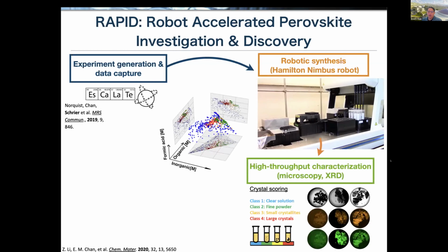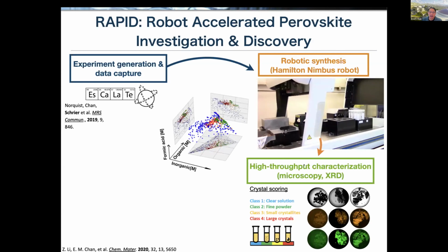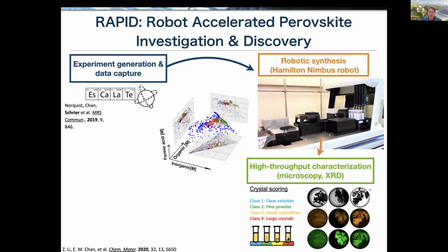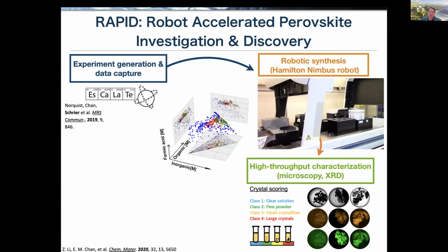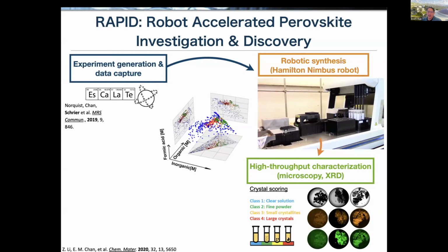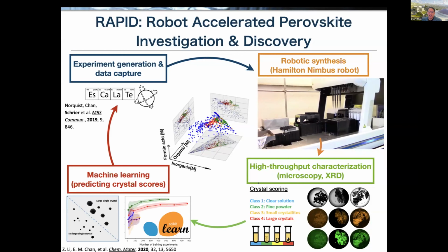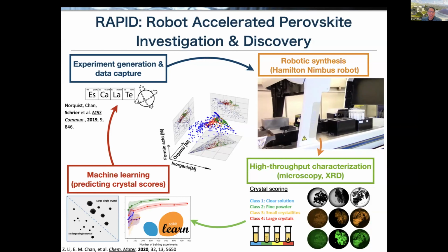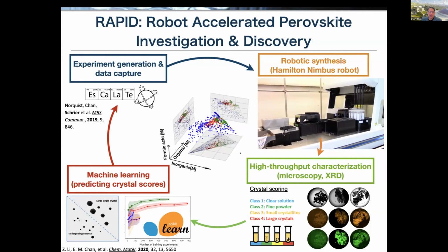So in this case, we're making perovskite nanocrystals exactly like Farnaz described in her previous talk. And so the idea was that these precursors would make the macroscopic perovskite crystals, and then we want to see how big the crystals were, because normally for crystal structure determination, you want to have a very large single crystal. And so we can use optical microscopy and machine learning to classify the size of the crystals or the quality of the crystals. And then we can develop models that, for example, predict whether you get really nice single crystals, for example, in these red spots, based on the concentrations of your precursors.